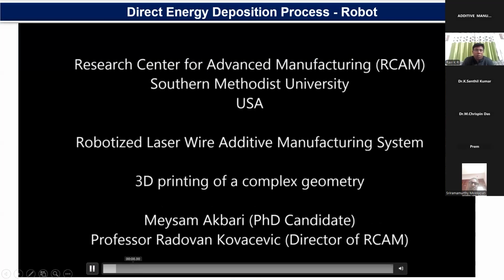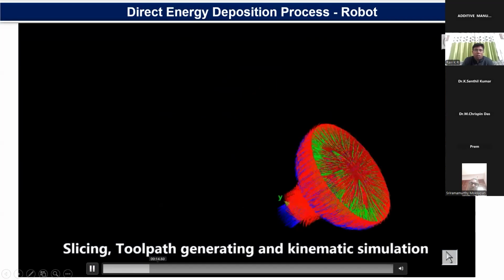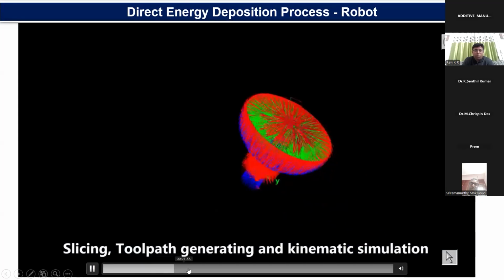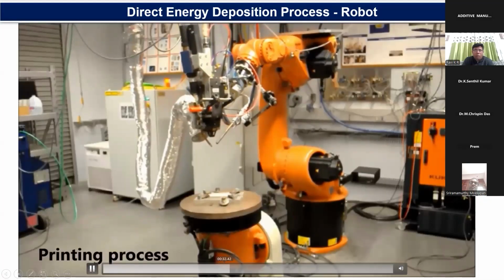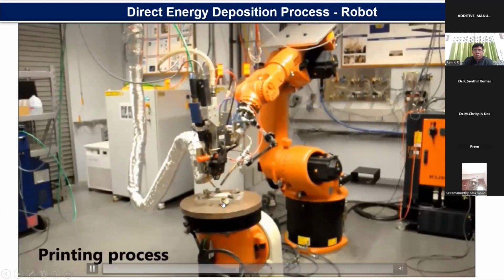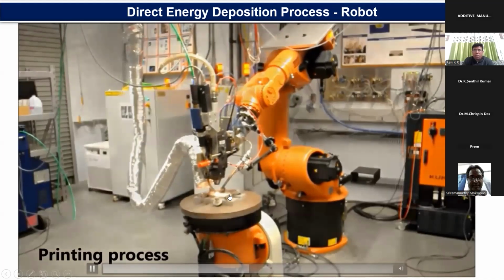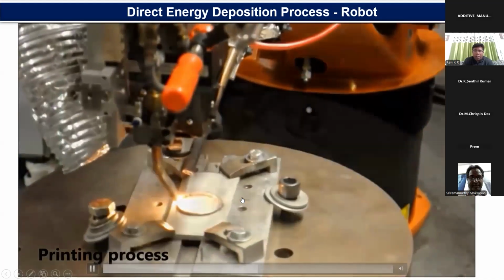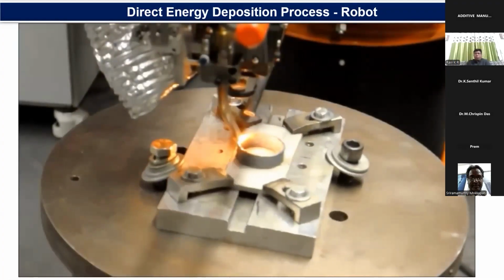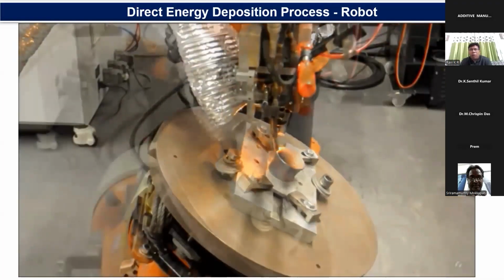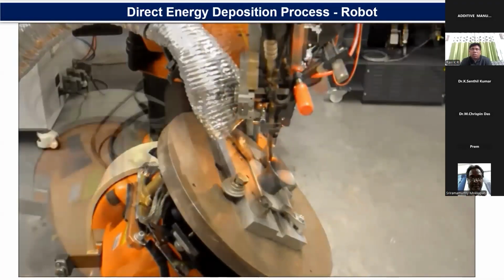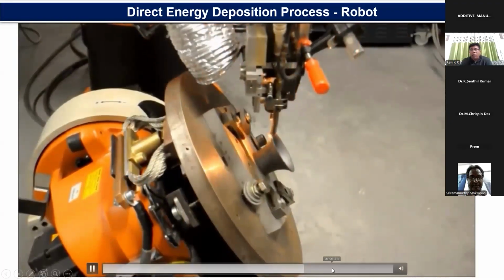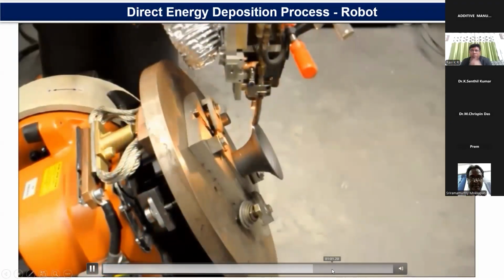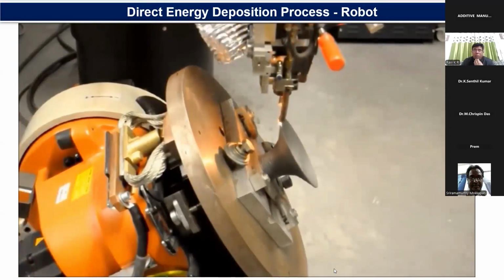The technique I have in my lab is very similar to this particular robot-based system. It is very similar, where you are going to have 6 axes on the top. The bed is going to have 2 axes. It will rotate and it will tilt, and the other 6 axes come from the robot. It's more or less similar. The major advantage is that you can go for very big components. In CNC, the volume of the part is decided by your bed size.